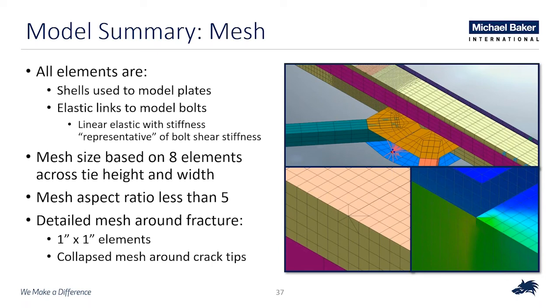Regarding the mesh, all of the elements utilized are shell elements used to model the plates. There were elastic links to model the bolted connections. And for these elastic links, a linear elastic relationship was used basically to be representative of the bolt shear stiffness. The mesh size away from the fracture location, that is the coarser mesh, was 8 elements across the tie height and width, with a mesh aspect ratio less than 5. So basically, no edge of any element is larger than 5 times the narrower edge.